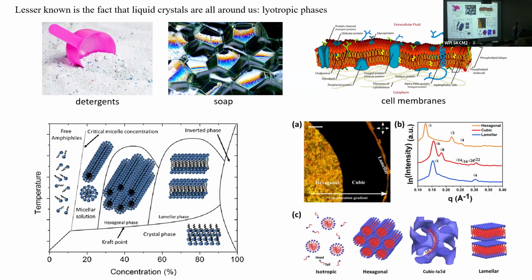This black part is actually the cubic phase, because that will not have birefringence either, so it appears black in microscopy. And then you have a thin bit of a lamella phase out here. And you can study this by X-ray diffraction, for example, and you can come up with quite complicated structures besides the hexagonal and the lamella phase. Especially the cubic phases are relatively complicated.